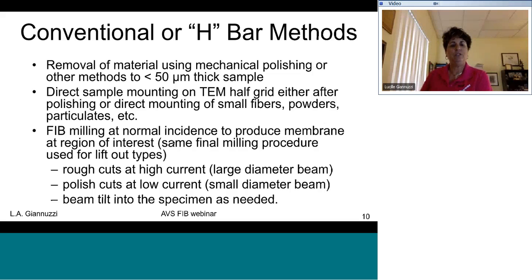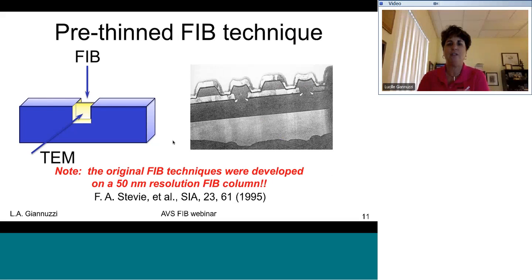And you want to tilt into the beam as needed. So it might be 1 degree, it might be 10 degrees, depending upon the sample that you're FIB milling, depending upon how that sample behaves and sputters, or redeposits, I should say, due to the V-shaping.